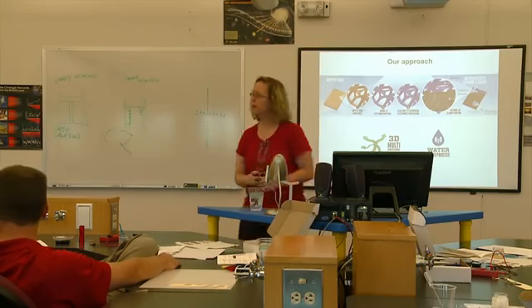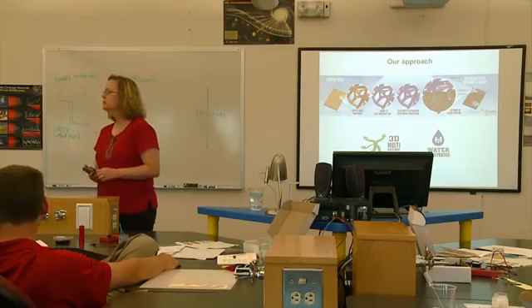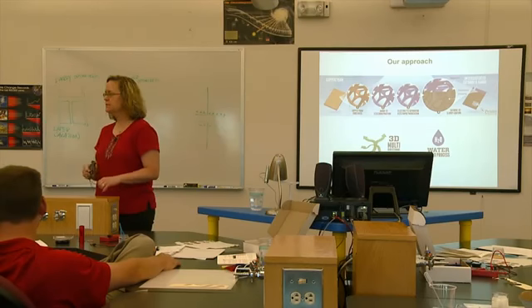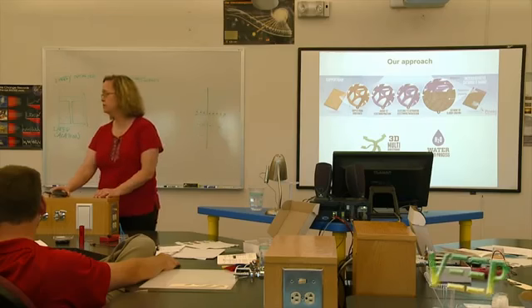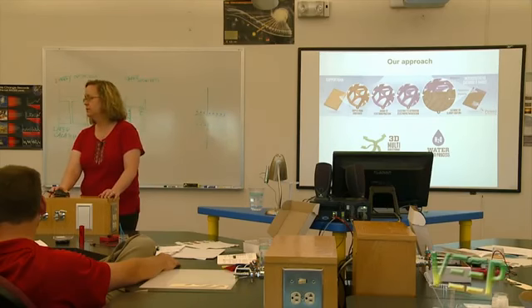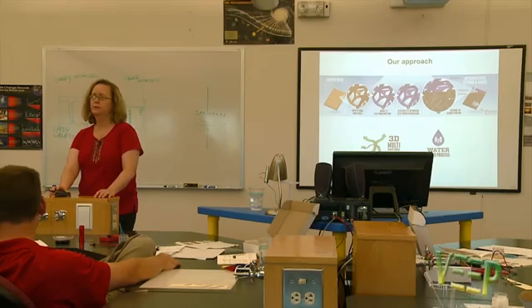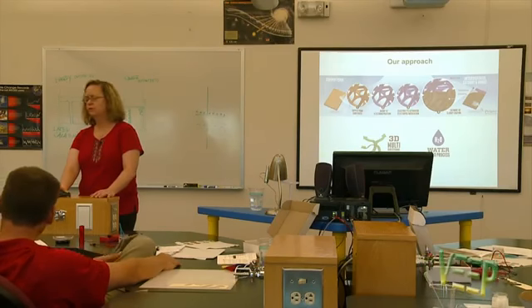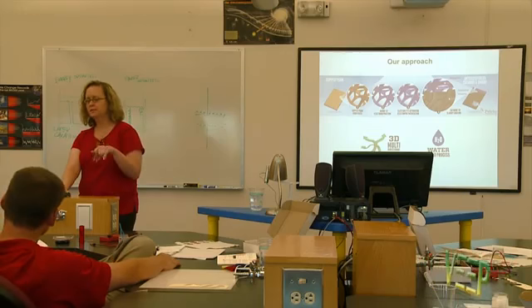Yeah? I don't know if I'm asking this question right, but what is the native open circuit voltage for a single cell in your chemistry? For us, it depends on the cathode material we use. So if we use lithium iron phosphate, which is what's typically found in power tools, it's about 2.8 volts. If we do use lithium cobalt oxide, we use a version of it that we make that has nickel and manganese in it to make it cheaper. So it's a lithium nickel manganese cobalt oxide. That one, we're at about 3.8 volts.